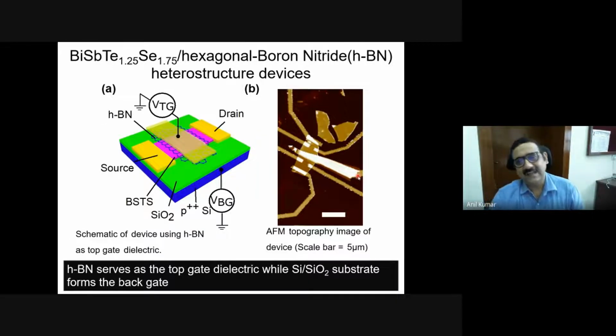Now, for any further studies to explore the physics or technology of these materials, you make devices by electron beam lithography. The device which I would like to make is a silicon substrate with silicon dioxide on top of it. We exfoliate this material, which is called BSTS, bismuth antimony tellurium selenide; in future I will call it BSTS. So this BSTS is exfoliated here, and then it is covered with hexagonal boron nitride, which is also a highly insulating material.